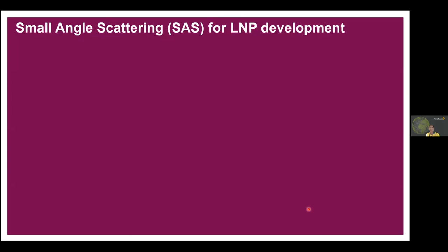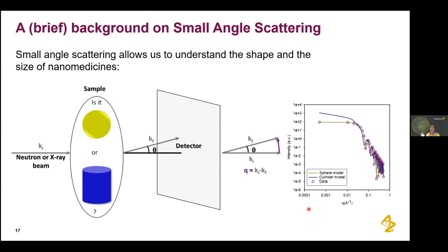That was when I was fresh back from my PhD and I said, why don't we do a neutron experiment? I drafted a SANS proposal and got beam time in Garching, Munich. I was particularly interested in using neutron scattering rather than X-ray scattering because we could do selective deuteration of either the lipid components or the solvent to produce different scattering profiles. With many components — cationic lipid, phospholipid, cholesterol, PEG lipid, and mRNA — we needed to figure out what to deuterate to highlight specific parts.